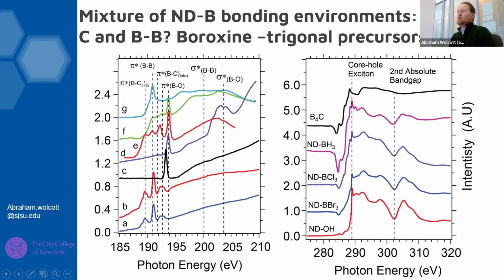So it's quite unique. And then as you go to higher energies, the sigma star states, so you can consider these are more of our delocalized pi bonding, and then these are our sigma-like on the axis between boron and oxygen bond formation. Now, if we look at diamond, and this is the cool thing about our XAS, is we can both see the boron coating and the diamond simultaneously. We can compare it to boron carbide, and we get these new states that are in the edge. So when we do the boron chemistry, we seem to have introduced new mid-gap states. This could be bad for spin coherence measurements, but I think it's worth pursuing both in the bulk and in our nanoscale material simultaneously. So just throwing those ideas out to the community.